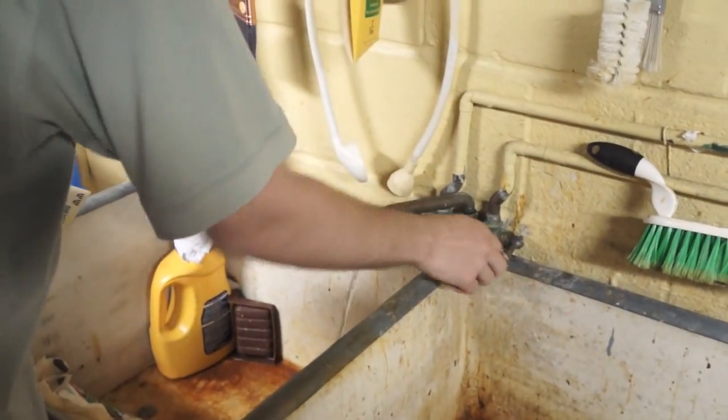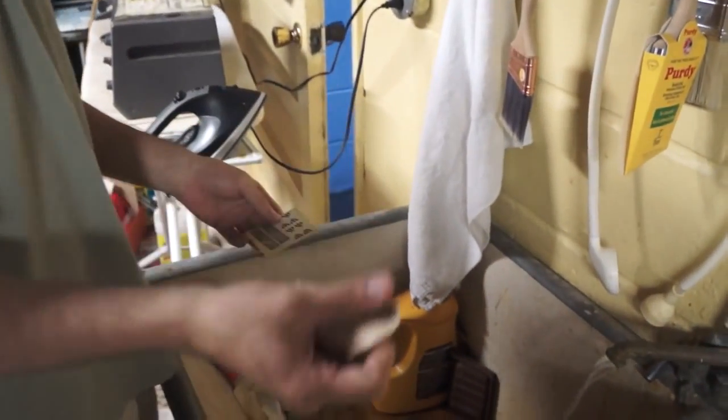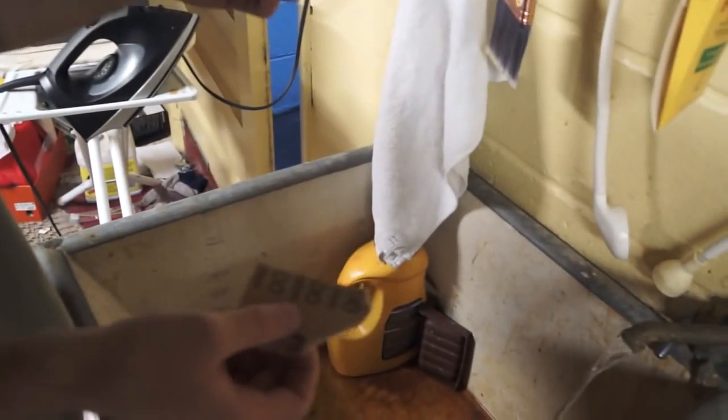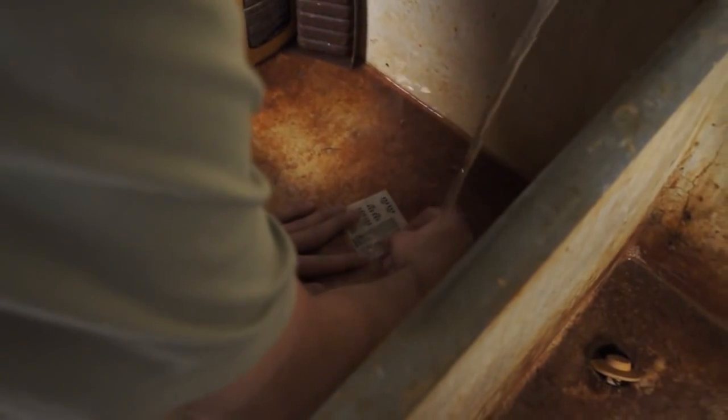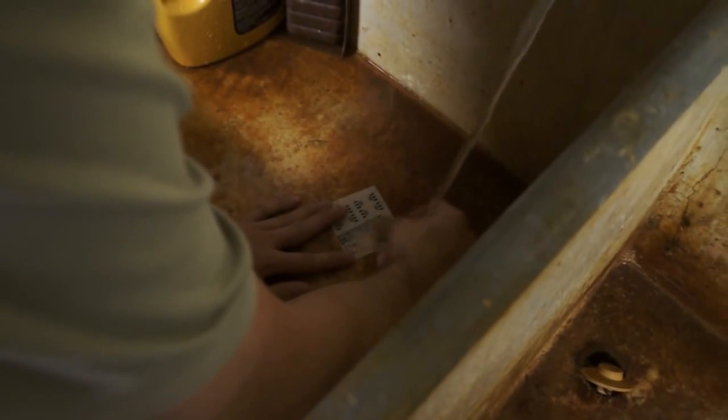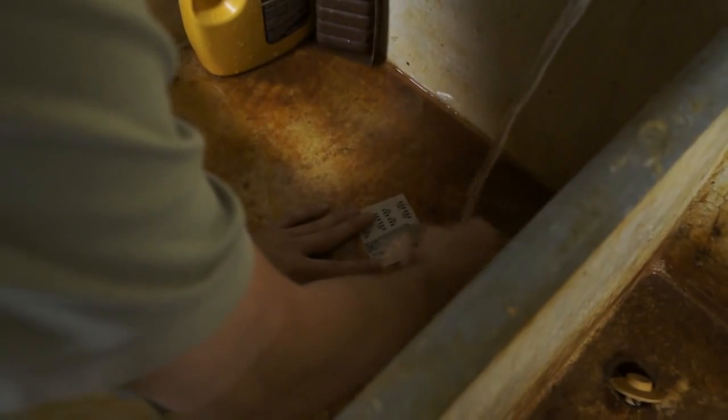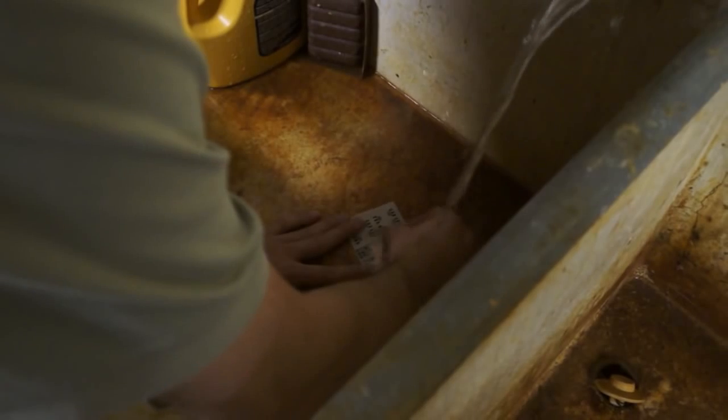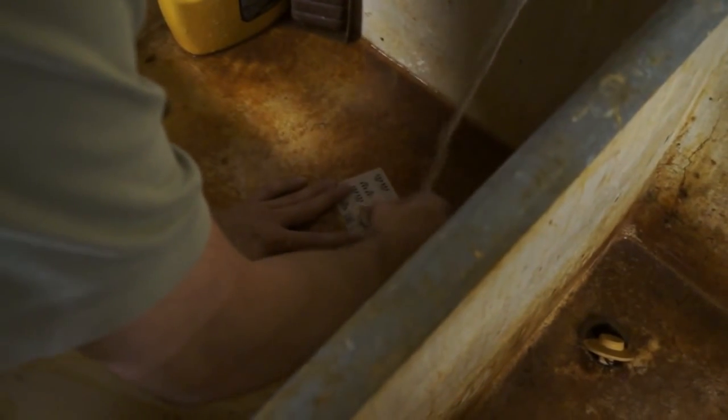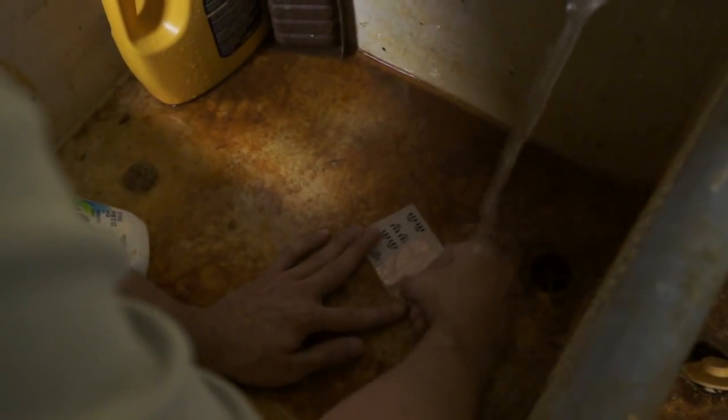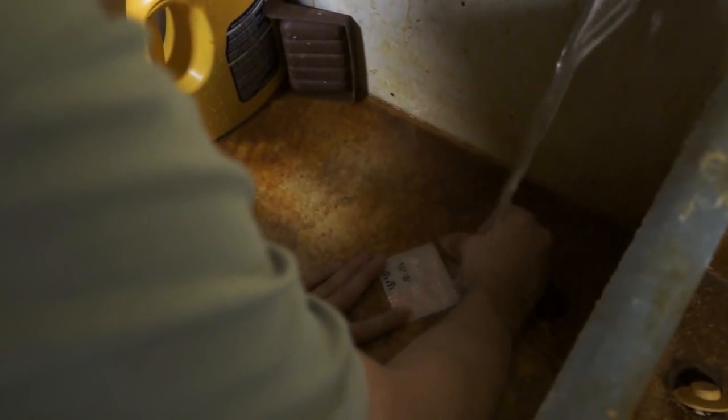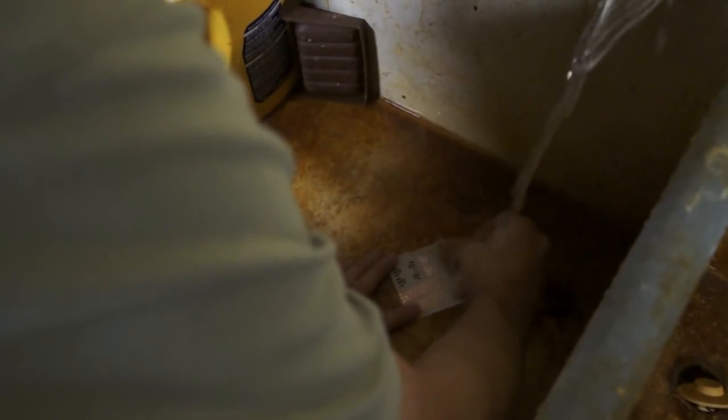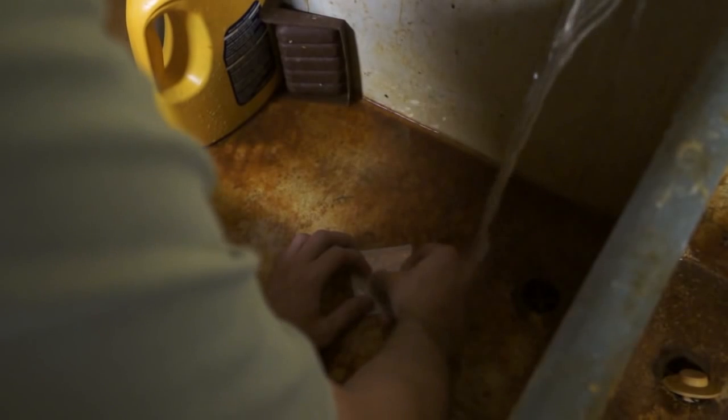So we have our silicone copper thing here with the backing still on. And the clear backing still on. And we've rinsed it off. I'm going to start up some water. And I found that you can use steel wool, but sometimes it'll rip the traces off. But if you use sandpaper, this is 100 grit. It works. 220 seems to work a little bit better. I just have the 100 on me. And you can just put it under running water and start sanding away very, very lightly. The sandpaper will pull the toner off. And it won't even make it so it's kind of ugly looking. This makes it so that, unlike using solvents like acetone, which can damage it and will cause it to look ugly, this will keep it so that the silicone itself will continue to be very white and it'll get all of the annoying toner back off.